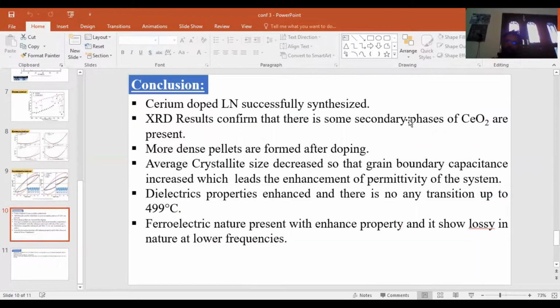Conclusions. Cerium doped lithium niobate successfully synthesized. XRD results confirm that there are some secondary phases of cerium oxide present. More dense pellets are formed after the doping. Average crystallite size decreases, so the grain boundary capacitance increases, which leads to the enhancement of permittivity of the system.